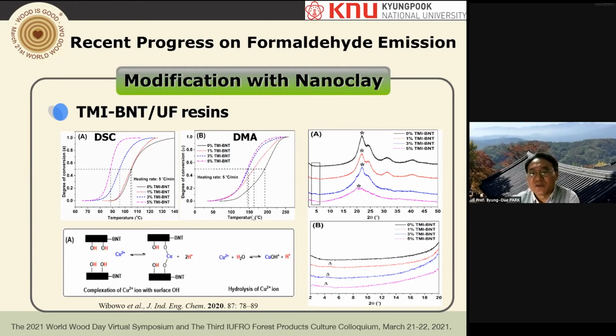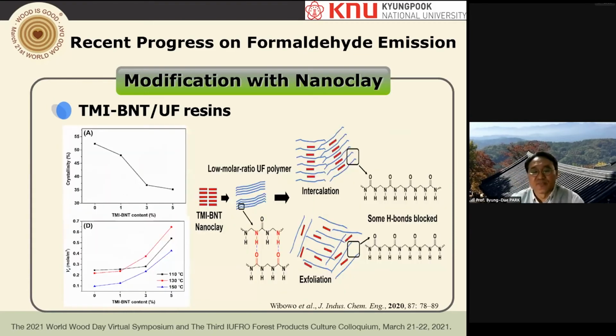And then we also looked at the XRDs. As you see here, this is the control, and this is 5% modified nanoclay. Compared to the others, the 5% modified nanoclay resin is almost amorphous. That means most of the crystal structure is gone. As you look at the rectangular bars here, that means some of the nanoclays are intercalated or some of them are exfoliated, which prevents making a crystal structure in the resins. Then we calculated the crystallinity of these modified resins depending on the modified nanoclay levels. As you see here, crystallinity decreased considerably at 5% modified nanoclay.